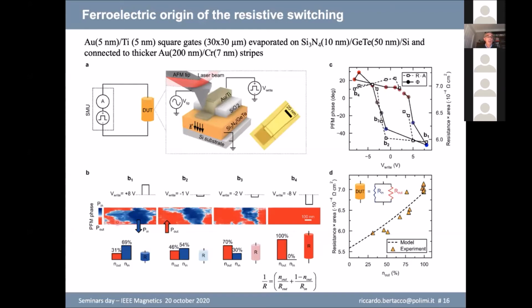So there is a big region in blue corresponding to polarization pointing downwards. And when you move to negative write pulses, you see that this blue region decreases in amplitude till you reach a red region corresponding also to polarization pointing upwards for -8 volt. And at the same time, it was possible to measure the change in the impedance. And this is the result.